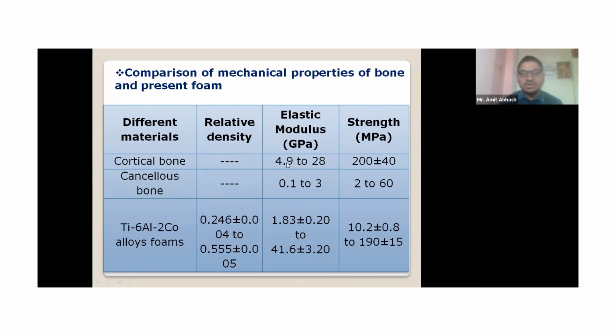In the case of cortical bone, you can see 4.9 to 28. If you go through the literature, someone has reported 30 or some may have reported 26, but around this only. And cancellous bone has a range of around 0.1 to 3. Average I have taken here; somewhere you can see 0.01 also, but that is a very special case. That is not the part of concern here. And strength is in the range of around 200 plus minus 40, and for cancellous bone the strength is 2 to 60.